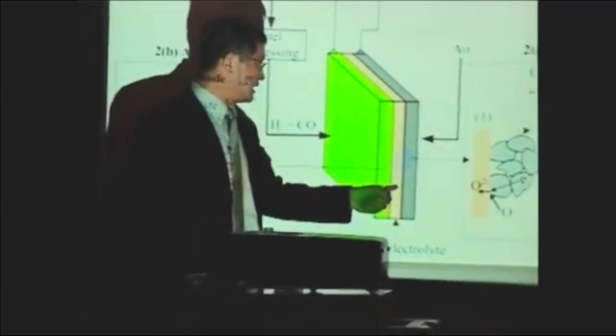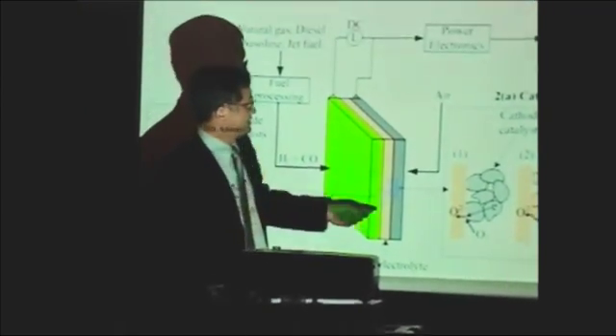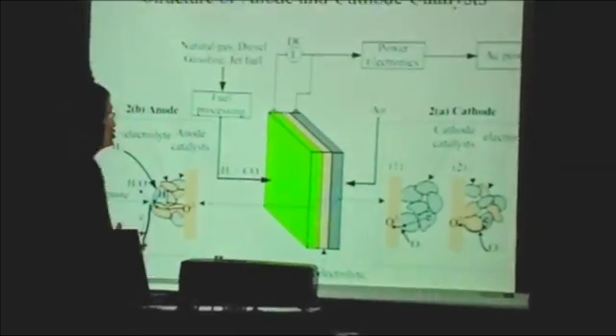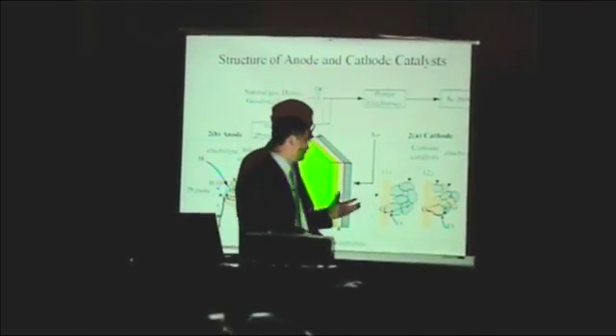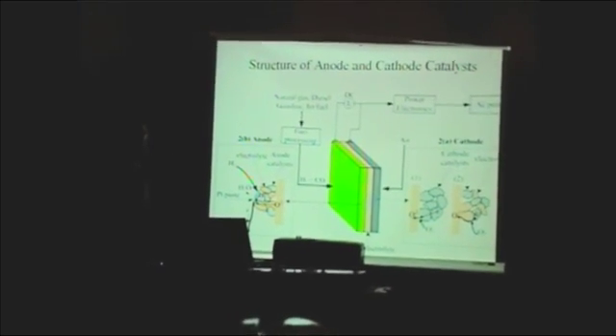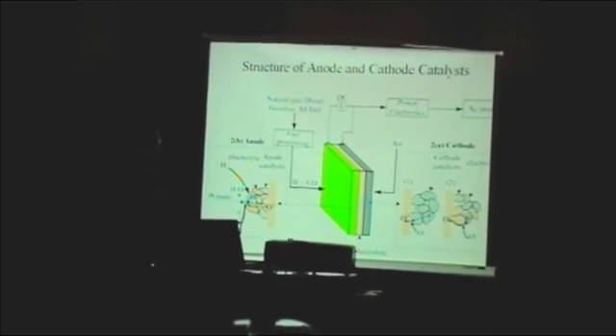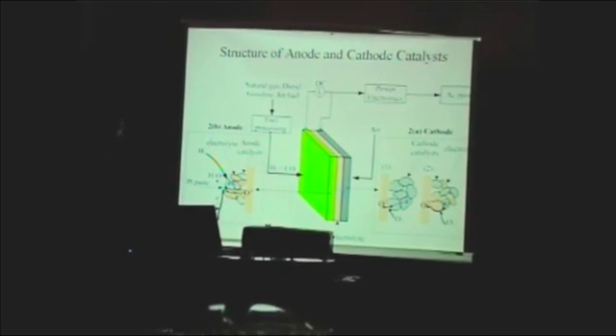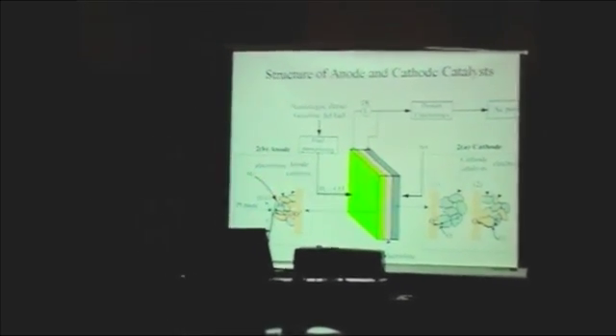Our research focus now is on how to design the nanostructure and microstructure of this catalyst surface. This research is very challenging because these layer materials are very difficult to stick together. They are all different types of layer materials, and thermal compatibility is an issue. If these materials don't have the same thermal expansion coefficient, as we heat them up, they always crack. So we have cracked hundreds and thousands of these in our lab, and we haven't developed a very good fuel cell yet. But we do prove that we can use hydrocarbons or plastic or carbon as a fuel to generate electricity out of this fuel cell by modifying the catalyst.